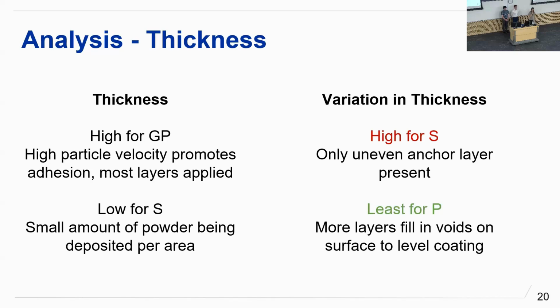The variation in thickness, we attributed the high variation for stage speed to only the anchor layer being present, and the anchor layer tends to be uneven because as the particles hit the metal, it plastically deforms the metal as the particles fracture, and this can make the surface uneven. And we attributed the low variation in thickness for the high passes to the fact that as more layers are deposited on the substrate, it fills in voids on the surface to level out the coating.